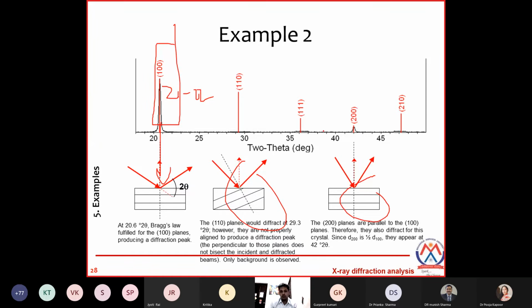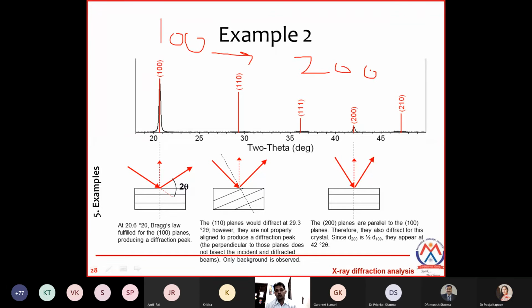One thing more I just want to convey over here. For every 100 plane, there is always a peak for 200 also. The intensity of the 100 peak is going to be higher, you can see over here, and the intensity of the 200 peak is going to be lesser. Similarly, if there is a 1-1 plane, you can have a peak for 2-2 also, if it is coming into that range. If there is a very small peak here, then the intensity of that peak is going to be a little lesser, because logically, the number of planes 100 has, the 200 plane is going to have much smaller numbers. We call it a second order, third order kind of plane, which we can see over here. So this is the second example of how we can interpret the location of the peak, where the peak is located.